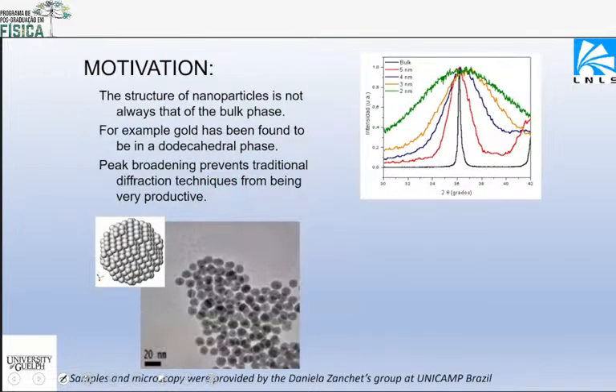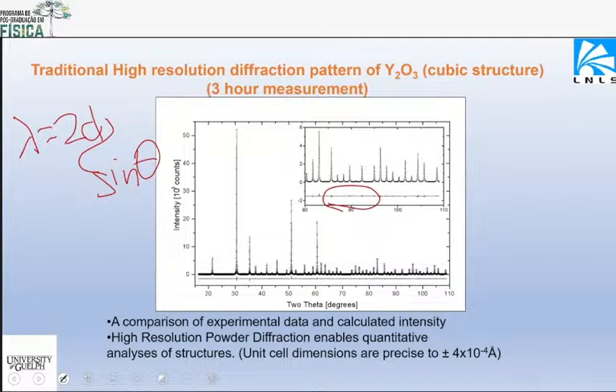So the problem, and this is what I want to show you, is that yttrium oxide is a classic way of doing X-ray diffraction. You crush up a sample, it'll be like table salt, and you put that in the beam, and you're going to get a nice diffraction pattern like this. You don't need a lot of sample, very little. What's causing the sharp peaks is the long-range crystallographic order in these crystalline grains.